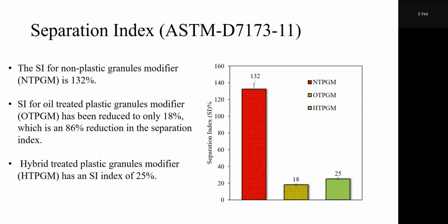Next, we want to see if they like asphalt. So we're going to do a separation test. We're going to dump each one of the plastics into bitumen and then measure how much they separate. We have a test called the cigar tube test, if you're familiar with it. If not, it's the ASTM D7173. You can check it out. We basically put it in a tube, we call it a cigar tube, and then after conditioning, we cut the top and bottom part, throw out the middle part. And then we compare the properties of the top and bottom.